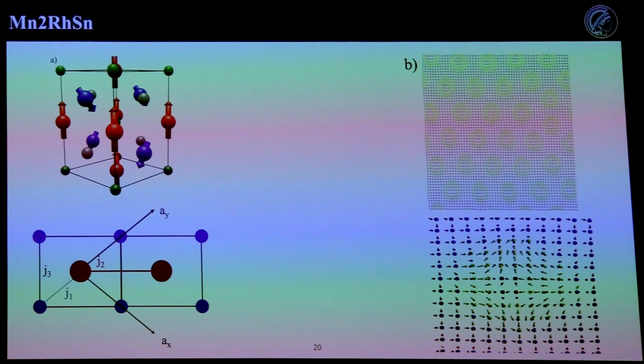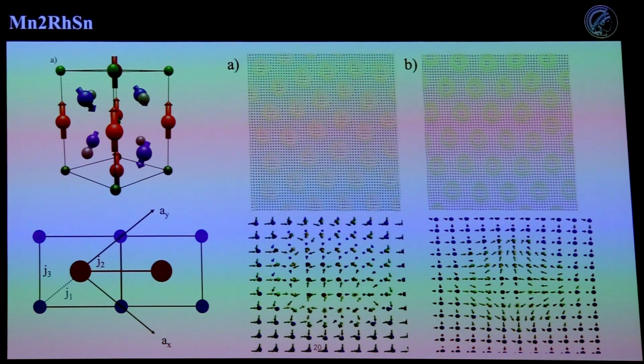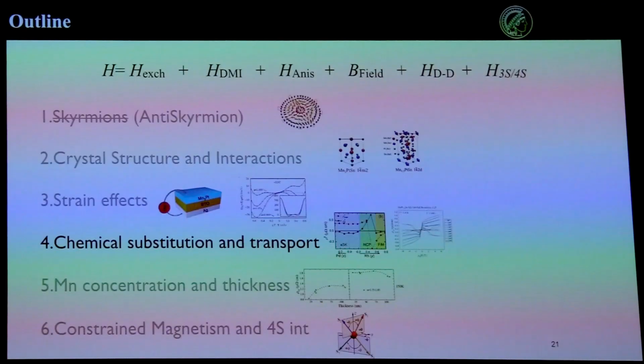And then we asked, what happens below the spin orientation? And we got something very weird here, actually. At first, it looked like a skyrmion, but when you look closer, it's a little bit more elliptical, and it still looks like a skyrmion. But you can see it's very asymmetric on this side and this side, where these two are very symmetric. What happens here is that it is an antiskyrmion, but it's very elliptical. In this case, when you do the numerics of it, you find that you have a charge for an antiskyrmion.